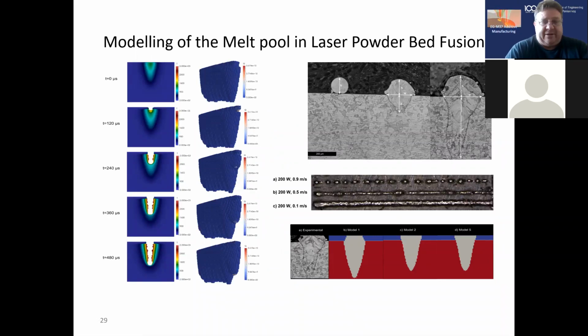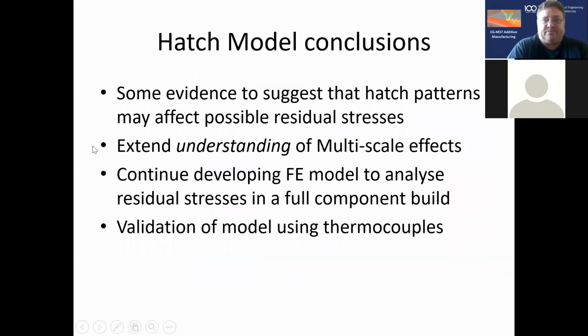That sort of modelling at the level of the melt pool is something that we've done a lot of at Swansea. This gives you an example of the development of a keyhole and how a keyhole develops. So that there is what a keyhole melt pool looks like, Chris. And you can see the top-down tracks, and here's some modelling of the keyhole as it develops. So it gives us that connection between the thermal and the residual stresses, and it gives us an understanding of how different hatch patterns can affect them.